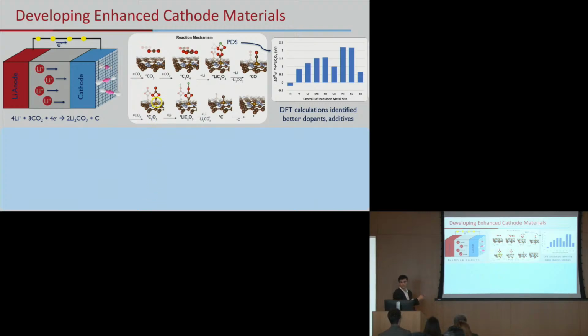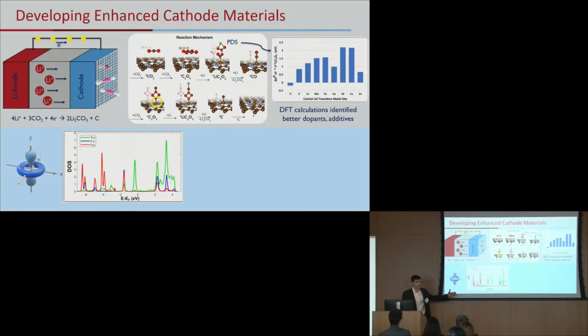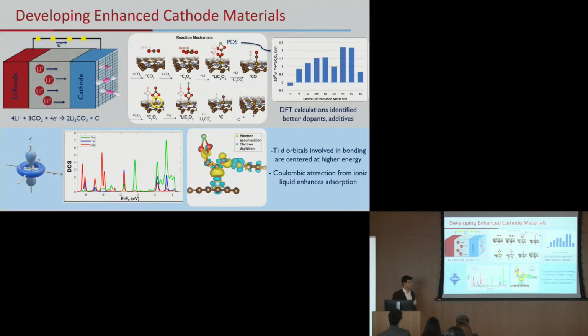So let's look at that transition metal. We look specifically at even individual orbitals on these atoms to see what kind of properties are contributing to these enhanced effects of titanium per se. So we look at the density of states, like the electronic structure, where these energy levels are, and we can find antibonding and bonding orbitals that these dopants are forming with the adsorbates. And we find that the electronic structure with titanium specifically has a really high d-band energy center in the orbitals relevant to the bonding. And that actually results in a really favorable adsorption dynamic that iron simply didn't have. And that's explaining why, on a deeper level, this is a better catalyst and why we're finding these enhanced results. And we can extrapolate that to new findings.